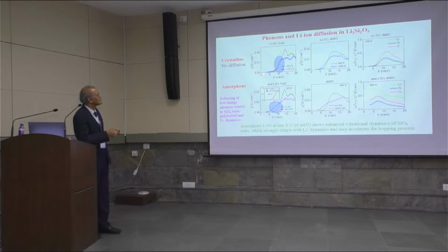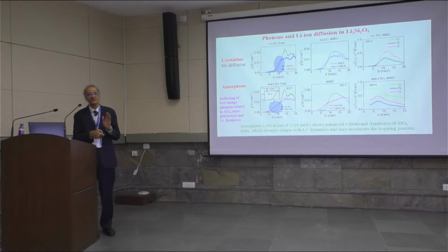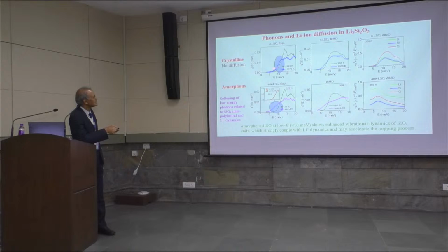Okay, so this is the phonon density of states. It's not exactly neutron intensity, but converted into the density of states as a function of energy. Normally we are familiar with the omega square or E square kind of density of states, but this is not just the acoustic region; some optic phonons come into play. At room temperature you have a certain density of states, and as the temperature is increased, there is a shift to lower energies in this material. But this is a marginal amount.